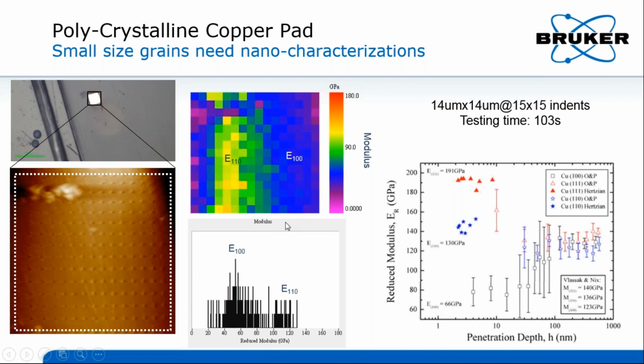Comparing the two peaks shown in the histogram, one is around 60 gigapascal and the other one is around 120 gigapascal. Comparing the two peak values with the three orientation modulus values of copper mentioned previously, it is easy to figure out the lower one is 100, and the higher one is 110. That is, we can assume that only two grains exist in the cross-section of the micropad, and one is 100, the other one is 110.